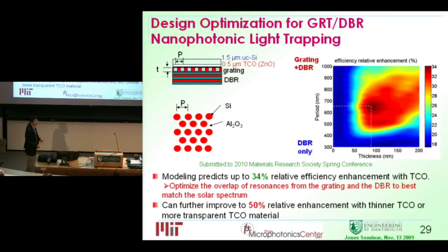So combining these two, we also need the adequate design, because we can design the period of the grating and the thickness of DBR, and this is a design map for that. So if you only have DBR, you get 18% overall relative increase in efficiency. But if you choose your grating correctly to match the solar spectrum, you get 34%. So this design can be further improved to 50% relative enhancement with a thinner transparent conductive oxide layer that's basically trying to allow the light through while also being conductive to collect the carriers.